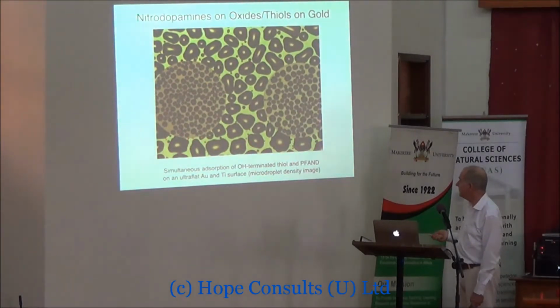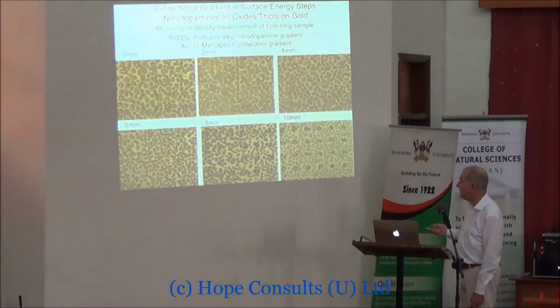I showed you this one before. This was where we used nitrodopamines here and thiols here, but you can actually do that in a gradient too. Now, in this case, we have a patterned surface with the titanium circles within the gold matrix. And we've done the dipping in two directions, one after the other. So we have a gradient on the gold that goes from hydrophilic at this end to hydrophobic at this end. And we have a gradient on the titanium that goes from hydrophilic at this end to hydrophobic at this end.